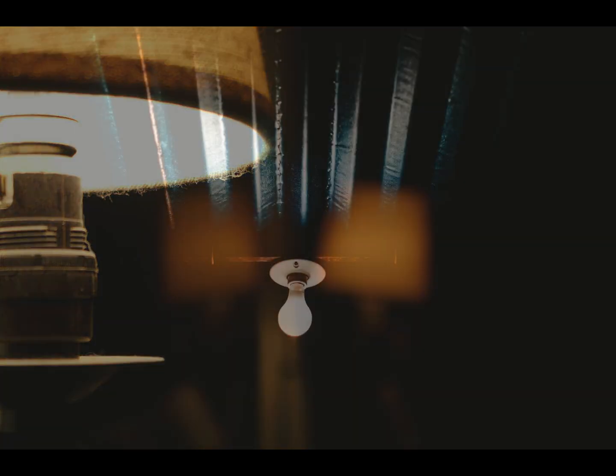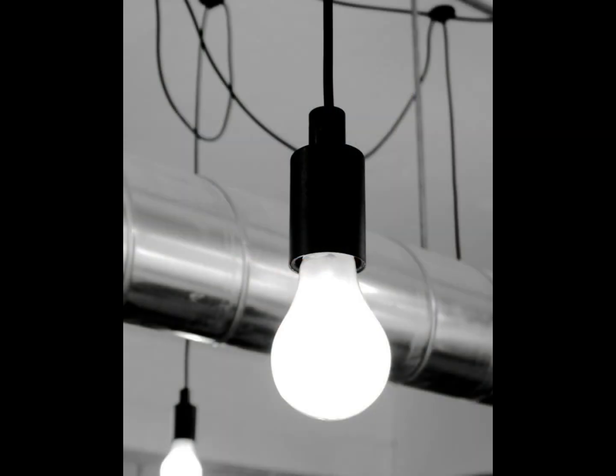0.0018 in. The advantage of the coiled coil is that evaporation of the tungsten filament is at the rate of a tungsten cylinder, having a diameter equal to that of the coiled coil. The coiled coil filament evaporates more slowly than a straight filament of the same surface area and light-emitting power. As a result, the filament can then run hotter, which results in a more efficient light source while lasting longer than a straight filament at the same temperature. Manufacturers designate different forms of lamp filament with an alphanumeric code.